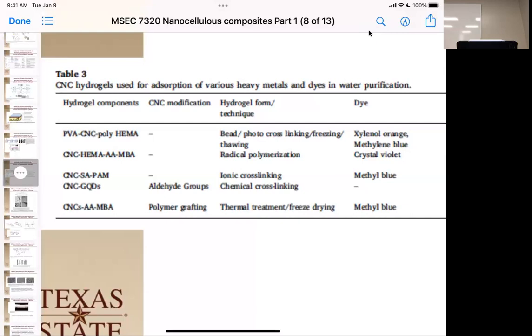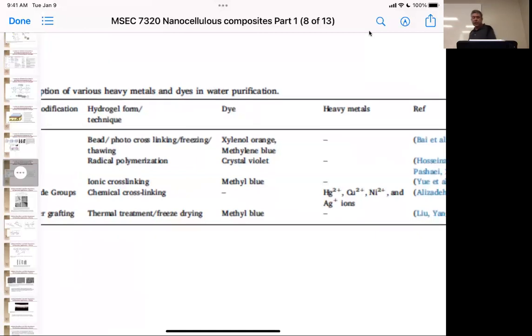But with the chemical cross-linking, the aldehyde groups react with any of the amines in the system to create an imine, and that gives us a chemical cross-link here. And they were able to isolate methylene blue. And when they did about the same thing with grafting and did a freeze dry, they were also able to. But the cool thing is the last one was also able to pick up divalent heavy metals and silver. Okay, we don't typically think of silver as a major contaminant, but things like mercury and nickel definitely are, and I believe that's copper.